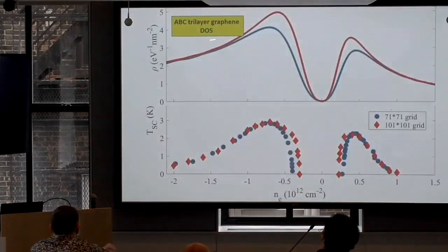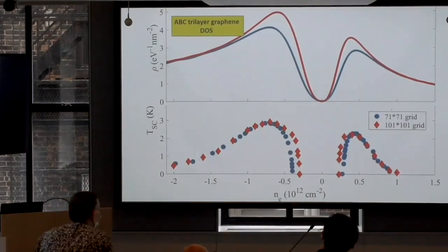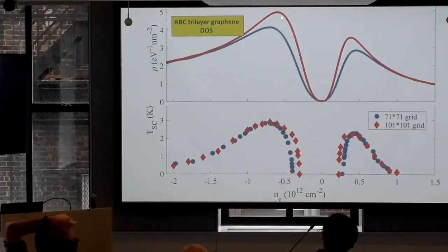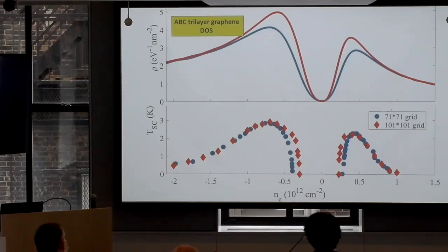So this is the density of states. Now do a Tc calculation. This is the self-consistent BCS, and you can see that Van Hove is where the superconductivity peaks, but it doesn't disappear right away. So the argument that there is superconductivity far away from Van Hove, so it cannot be electron-phonon, is just incorrect. And this depends a little bit on the grid. Young is very careful, and it has converged but not completely. But I was happy publishing this. And so this is the result.